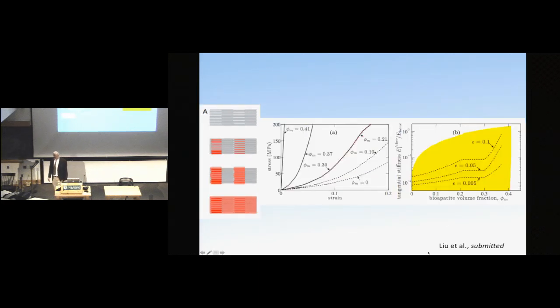This involves a few steps of homogenization. And the first step of homogenization is to combine the material properties of this nonlinear collagen fibril that were obtained not directly, but only through molecular models, so atomistic-like simulations. And then see what happens as increasing quantities of the mineral phase works its way into the gap channels, and then works its way onto the outside of the collagen fibrils, and then finally grows to encompass the entire fibril.